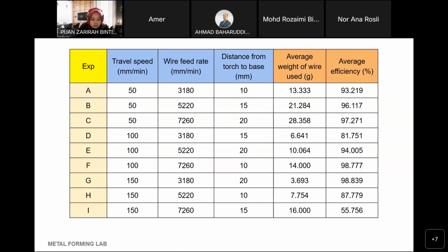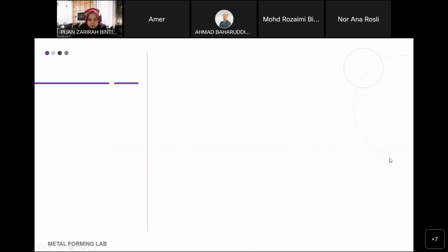This table presents the data of their experiments. As you can see here, the highest efficiency of the machine is when using the highest travel speed, which is 150, and lowest wire feed rate, and lower distance from torch to substrate, which is 10 mm. The efficiency of this experiment is 98.839%. So efficiency calculation they get from Benton C in 2021.